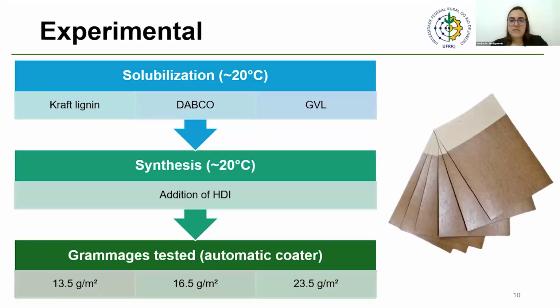So the formulation involved mixing lignin, GVL, and DABCO at around 20 degrees Celsius for 15 minutes. Then we added the HDI at the same temperature and left it stirring for around 20 minutes. And then we let the formulation rest. First it rested for an hour at 20 degrees Celsius. Then it went to an oven at 105 degrees Celsius for 10 minutes. And for the last 2 hours, it rested again at 20 degrees Celsius before application in an automatic coater.